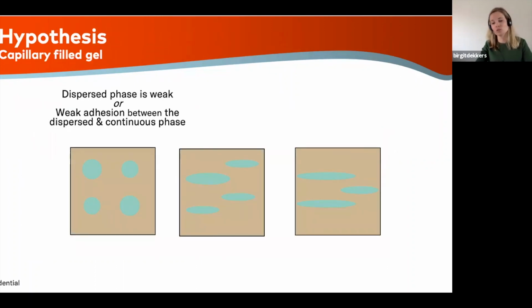So what does this do? This microstructure, what we hypothesized is that this dispersed phase that you see in the microstructure is weak, or that there is weak adhesion between the dispersed and the continuous phase. If you then start pulling these types of structures, in the case that you are not able to deform the structures, then you see that the weak surface is in both directions the same.